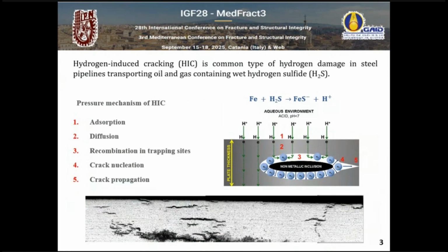One of the most intriguing questions is, if these trapping sites are all over the microstructure, why do some cracks nucleate rather easily, like this big crack that we can see here, and why are some other cracks very small? As we will see in the next slides, there is also a delay in the nucleation of cracks. Some cracks nucleate as soon as the plate starts absorbing hydrogen, and some other cracks can take days or months to form. Why? We don't know yet. That is what we will try to find out in this research.